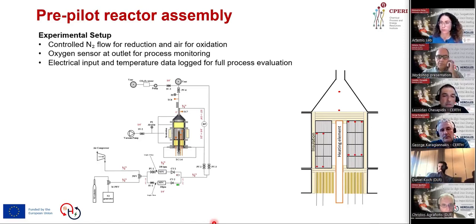During operation, we used nitrogen as the inert gas for the reduction phase and air for the oxidation phase. Both flows were regulated using a mass flow controller to precisely control the flow rates and the residence times. At the outlet, an oxygen sensor continuously monitored the redox reaction, allowing us to evaluate the conversion and the kinetics of the process. The electrical power input to the heating element was also monitored together with thermocouple readings to obtain a full energy and temperature profile of each cycle. So this comprehensive data set allows us to analyze the efficiency and the stability of the system under this cyclic operation. The next slide, please.